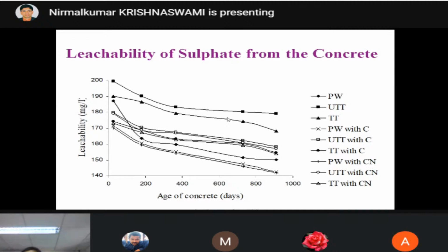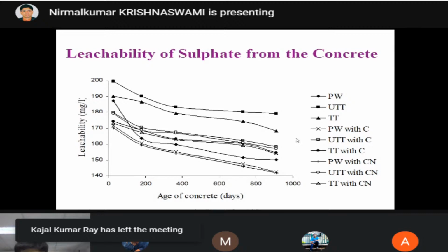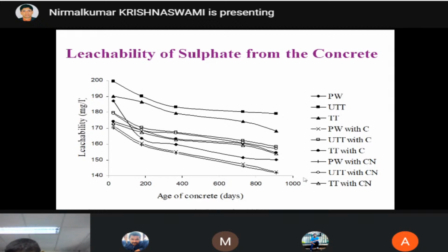Then leachability. Leachability is a very important environmental parameter. When we construct a building and it is subjected to rainfall, the rain falls on the building and the water gets into the soil, so it may affect the soil properties. For that I carried out this leachability test. Here, without adding admixtures, it is around 200 milligram per liter, but when admixtures are added, it is reduced to almost 180 milligram per liter. One more point to observe is that as the days increase, the leachability is getting reduced. If we continue for 3 years, 4 years, 5 years, at one point of time we will have a minimal leachability of 140 milligram per liter.